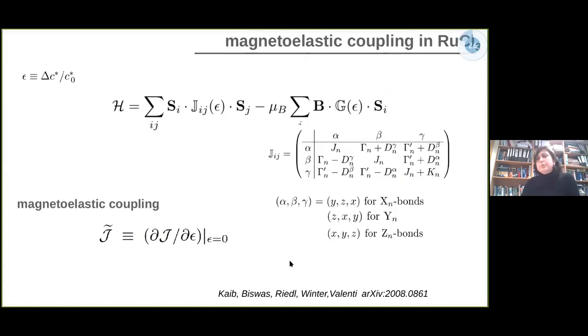But now what we want to do with that is, because we have from ab initio all these structures at different strains, we can now investigate how the coupling interactions, how the exchange interactions change as a function of this strain, as well as how much also the g factor changes, because we are changing very much the environment of ruthenium. So this is now the compact form of all the magnetic interactions in this system, where here you recognize the gamma, the Dzyaloshinskii-Moriya, the Kitaev, all the terms that are important.